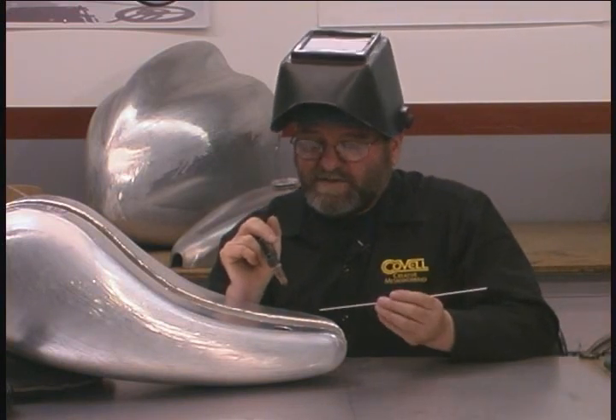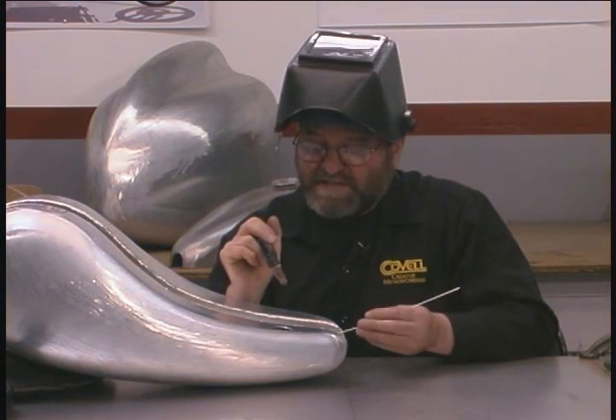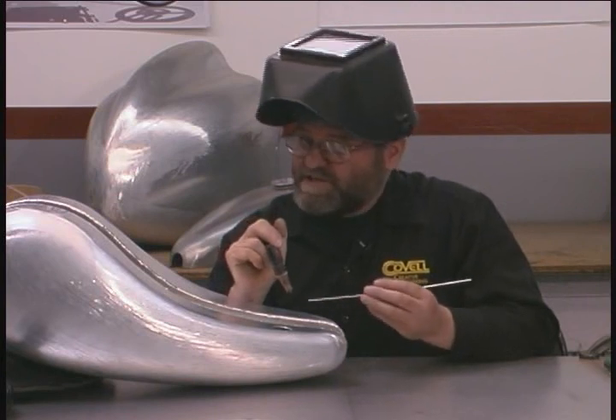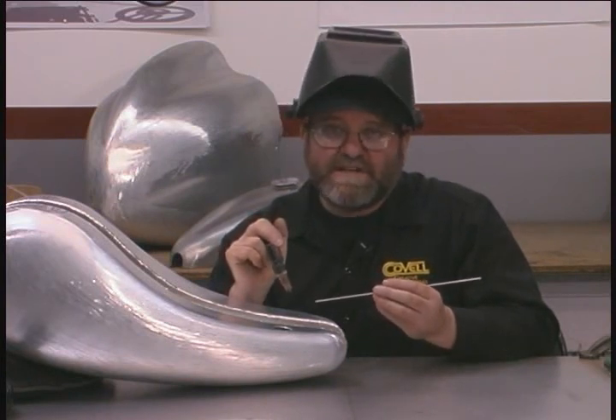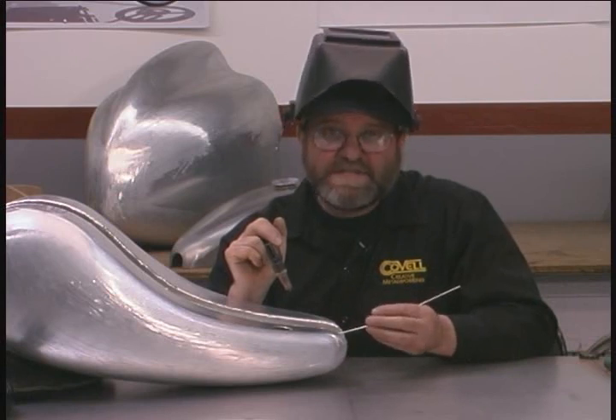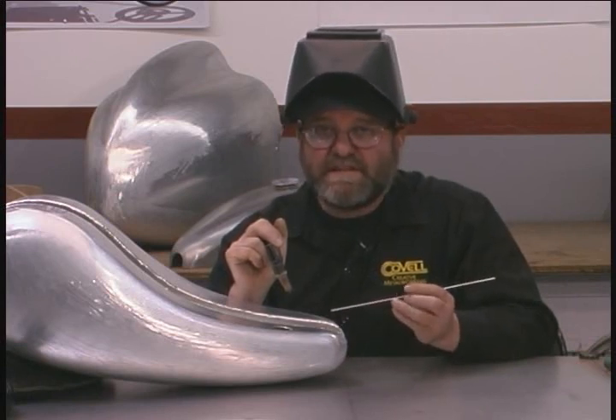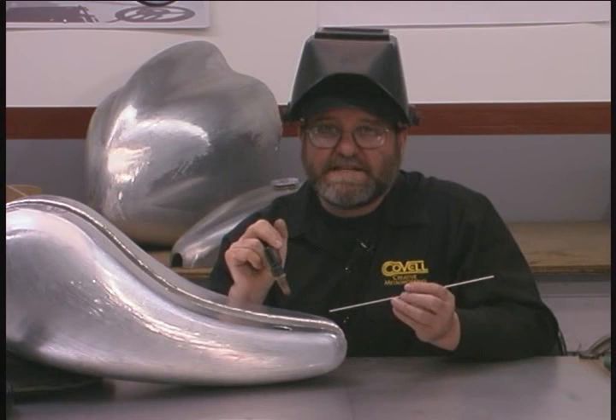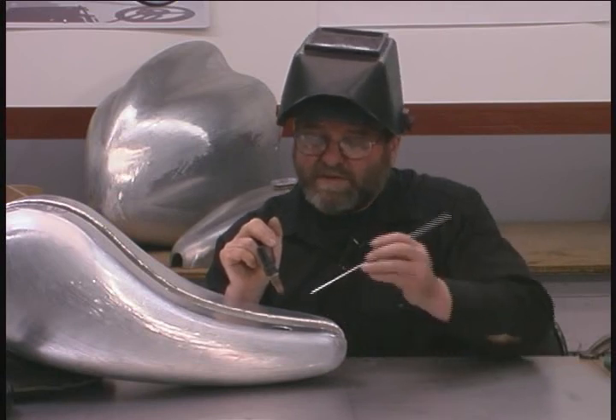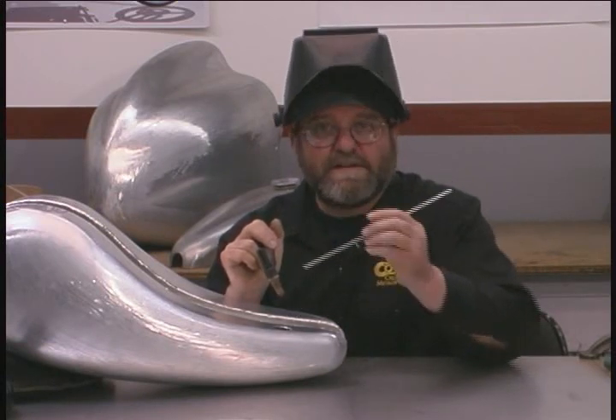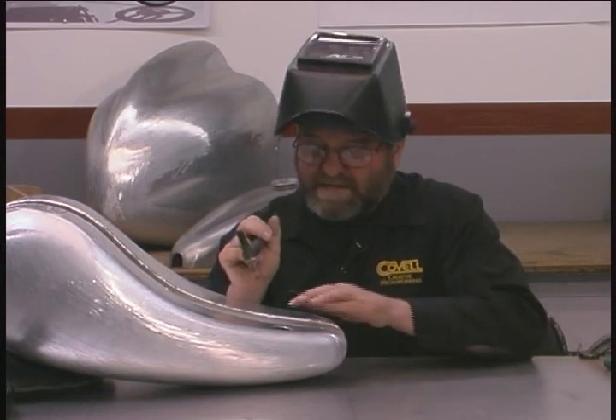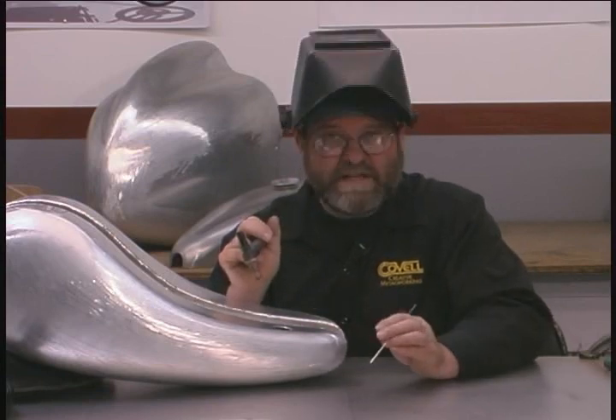Okay, so I've used the TIG welding machine to join the tunnel to the tank. Unfortunately, you can only use a TIG for this process because we're joining 1/8-inch material to 80 thousandths material. That's just not possible with an oxyacetylene torch. So we'll go ahead and weld in the threaded bung for the petcock. We'll sand this weld to make it smooth, and we'll have ourselves a gas tank.